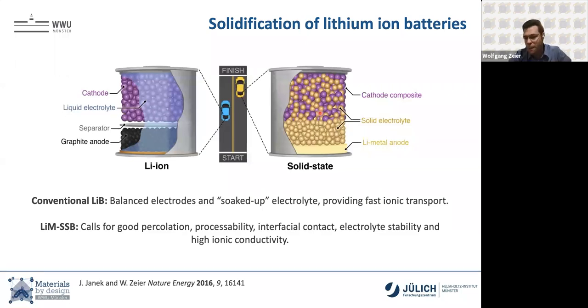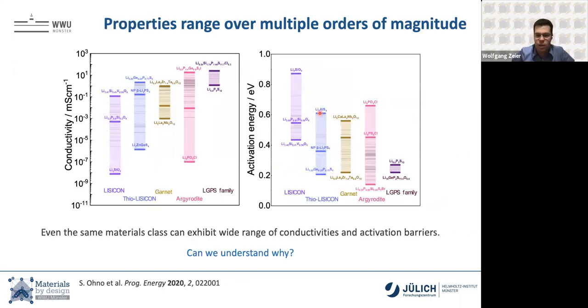If you have a bad ionic conductivity, you have a high resistance between your electrodes, and your battery's just not going to work. And so there is this push of going solid in the battery community, and on top of that, we need to really have fast ion transport. And this is something I want to talk about today. Why is that important? Well, ideally, and I'll say this now, and I'll probably kill that statement at the end of my talk, but right now we roughly need 1 millisiemens per centimeter of an ionic conductivity for